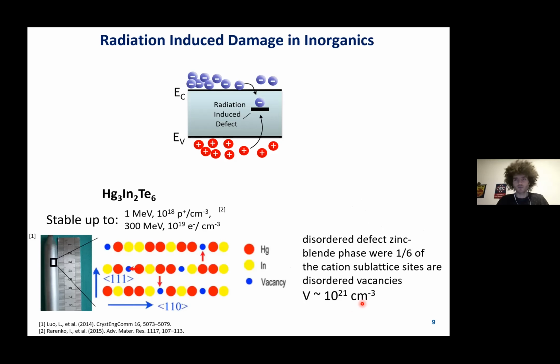So then one example of the other extreme is mercury indium telluride. This actually is a disordered defect zinc blende phase in which every sixth position is actually a disordered vacancy. Because of that, this material is extremely radiation tolerant. However, it's also extremely difficult to make transistors or solar cells out of this device. You can, for example, not dope it, and you're left with Schottky junctions.